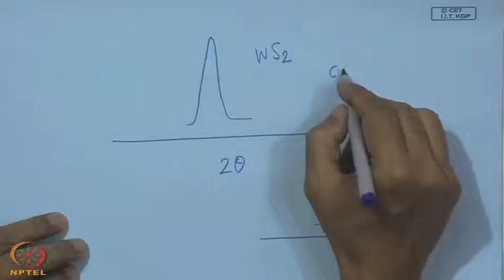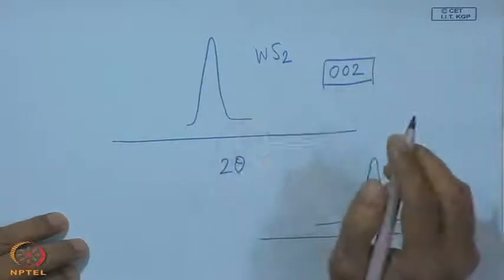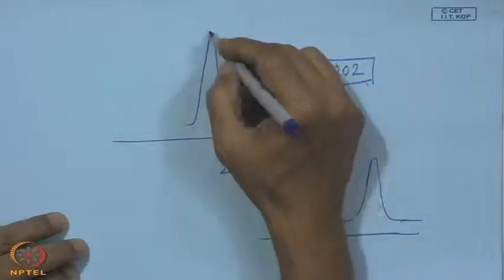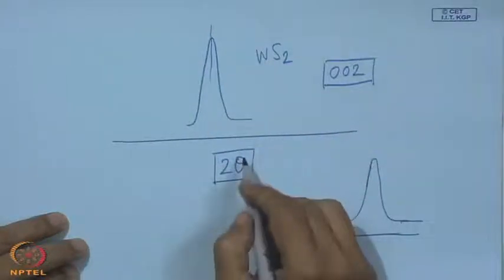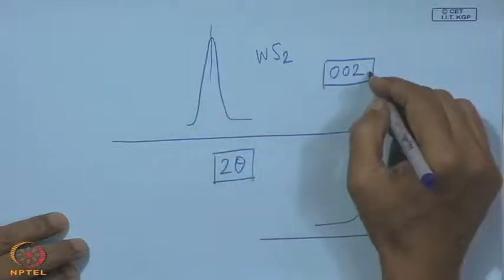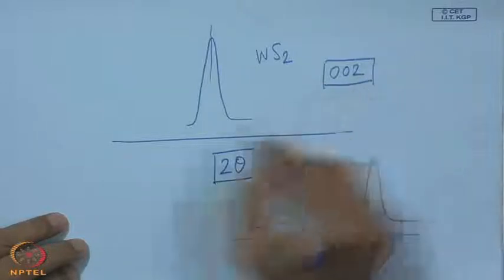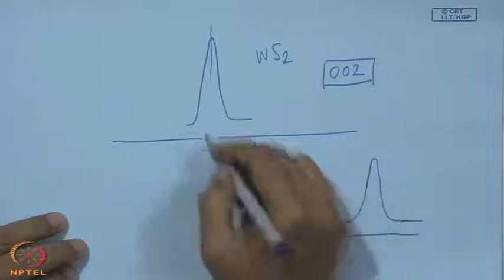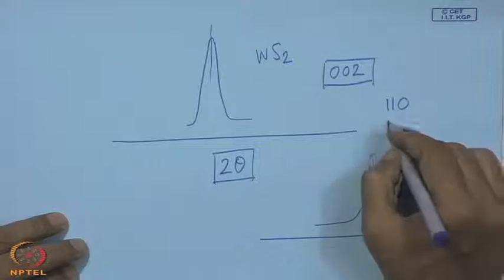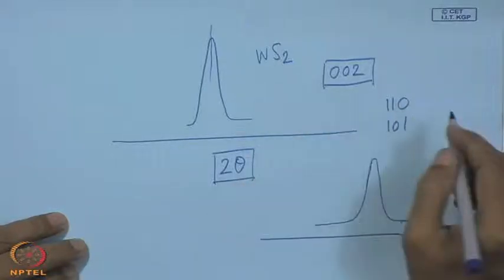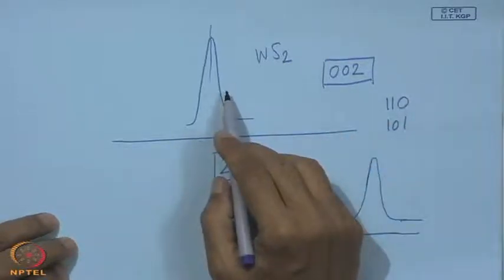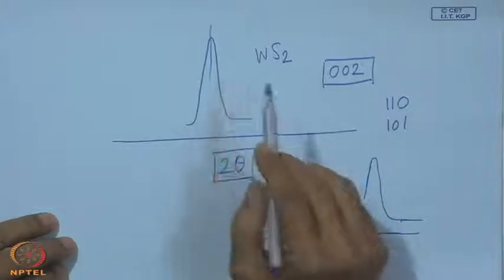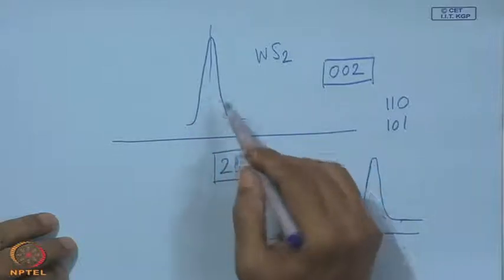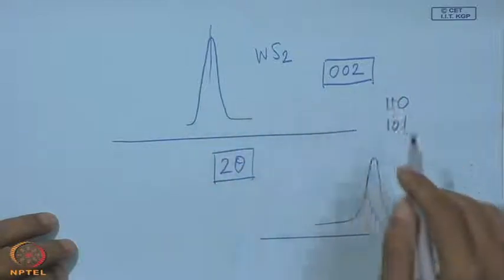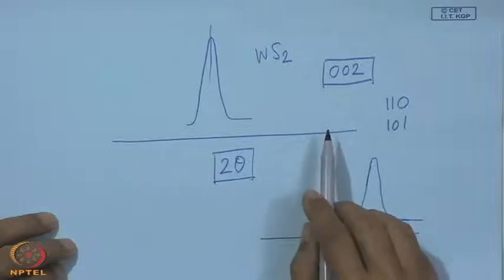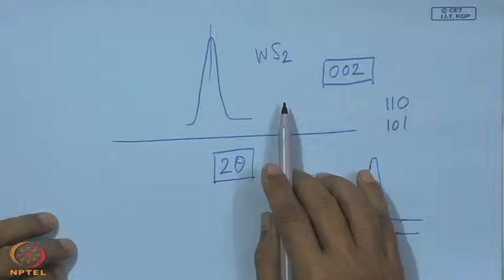In this case, what we are interested in is the 002 basal plane, and this XRD diagram will give us a clear indication of this 002 plane depending upon the value of 2 theta. So, for a particular value of 2 theta, if this peak is indicated, we can immediately recognize whether it is the 002 plane that is parallel to the substrate surface. If it is not the case, if it comes at a lower angle, there are other planes, like the 101, which appear at a higher angle. If those appear, then that is also a clear signal that this coating cannot be a good candidate for lubrication, it cannot give lubricious property, and it cannot have satisfactory performance in that particular activity. So, these are a few illustrations and examples of how this XRD diagram can be used.